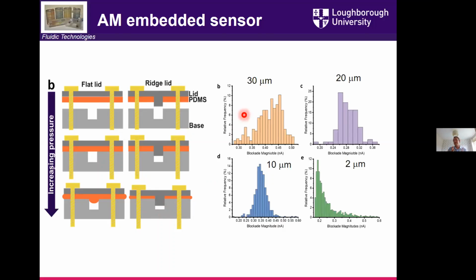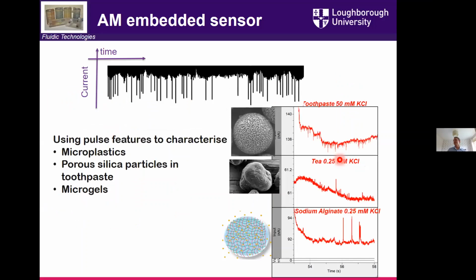And then with a simple SLA printer that's printing 100 micron features, you can start to measure particles and emulsion droplets all the way down to 2 microns in size. And that pushes it into a different realm. Now we can measure the smaller droplets, but also measure things like bacteria in other examples of the analytical processes that we look at. To give you a feel for how we could use this in droplets, what we also did with this sensor was to not just put solid spherical particles through, but other types of materials.